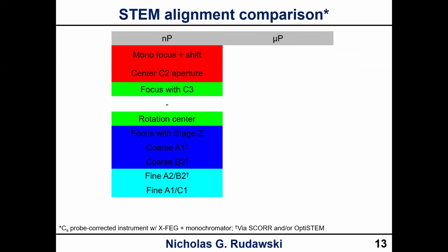The last thing I want to mention here is just the nuts and bolts of aligning the microscope in both of these modes. So in nanoprobe mode, this is all the hoops you've got to jump through. Adjust your monochromator, focus and shift, center your C2 aperture, focus with C3, beam tilt, which is rotation center, focus your image with stage Z, and then you have to do your aberration tuning: correct coarse A1, correct coarse B2. Then you can do fine A2, B2, and fine A1, C1. Of course, we have SCORR that we can use, and OptiSTEM if you have that as well.